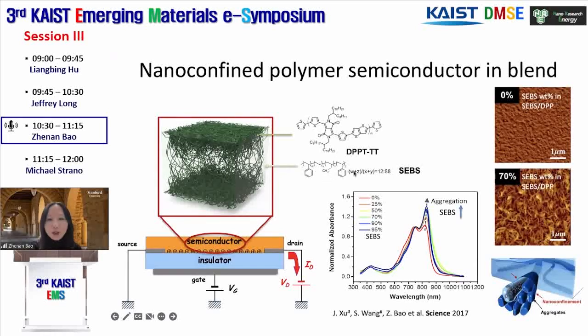And then, on the other hand, we noticed that compared to the neat polymer, which the AFM shows a featureless structure, with the addition of the insulating polymer, it results in these nano-confined nanofiber structures. And these structures were already formed in solution because in the solution UV-vis, we can observe the aggregation absorption peak increase in its intensity as we increase the amount of insulating polymer we add into solution.